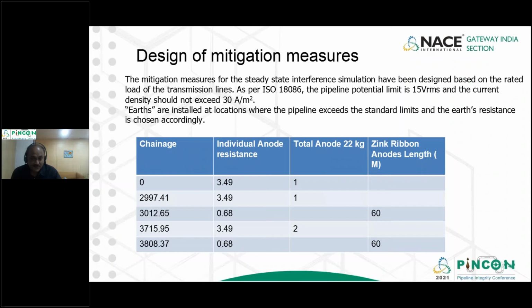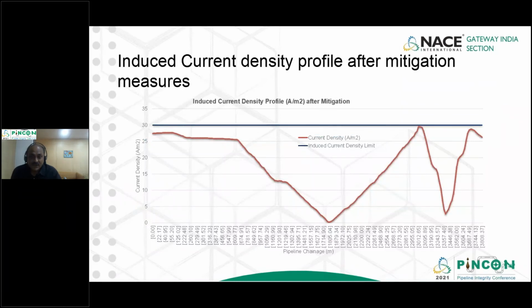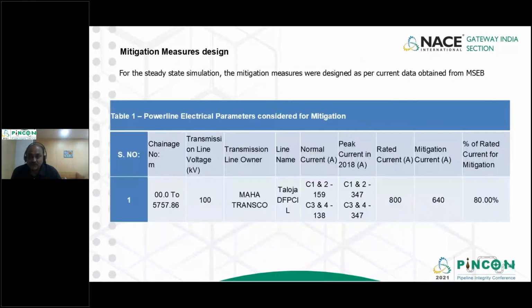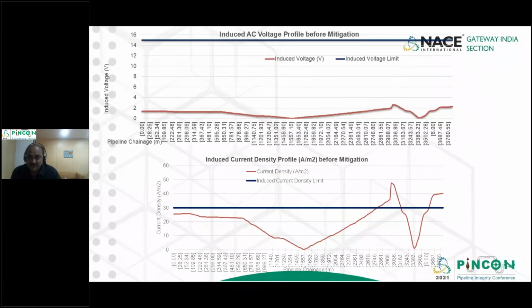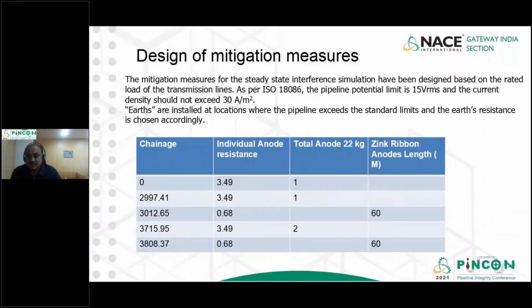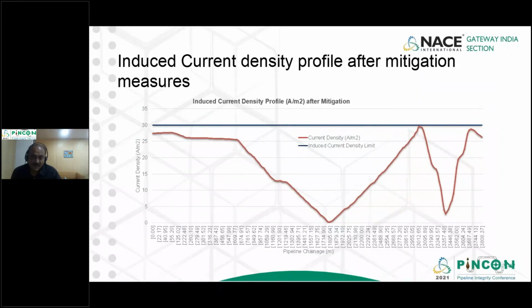At 0 to 2997, one anode, between 2997 to 3012, and between 3715 to 3808, we have installed 2 anodes of 22 kg each. And then zinc ribbon, we have installed 60 meters at 3012 chainage and 60 meters at 3808 chainage. These are the places where, if you go back, you will find that we were having issues. Post doing this, you see the current density after these mitigation measures: we are well below 30 amps per meter square.